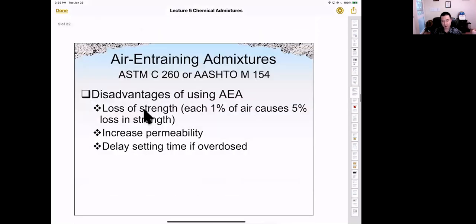But the worst thing about air entraining agent is it will reduce the strength. So for every 1% of air will cause 5% reduction in strength. So that's why we have the optimum dosage of air around 7 to 8%. Okay, too much air, the strength will be too low.